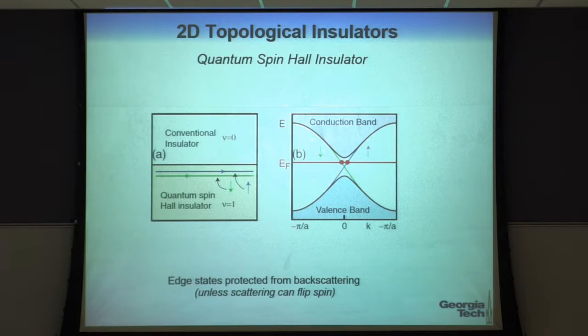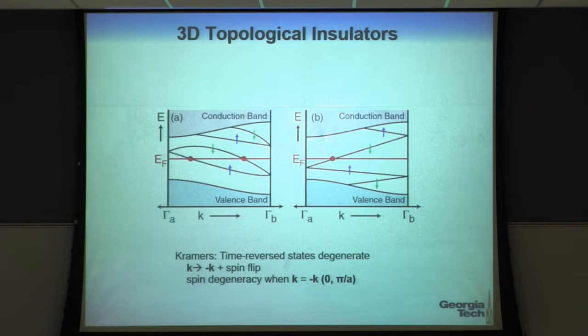So the two-dimensional topological insulators, or quantum spin Hall insulators, they also have these edge modes. There is a topological invariant, which is different from a conventional insulator or vacuum, and therefore these edge modes have to be there. Okay? They have to occur. The band structure of this looks like so. Now I have 2 states, one with spin up, one with spin down. And it's metallic because the Fermi level has to cross those states. It's really sort of a half metal because spin up and spin down are not doing the same thing. Okay, so in this band, I don't have both spin up and spin down. I've just got spin up. In this band, I've only got spin down. Okay. So these edge states, as I explained, are still protected from backscattering for the reasons I said.